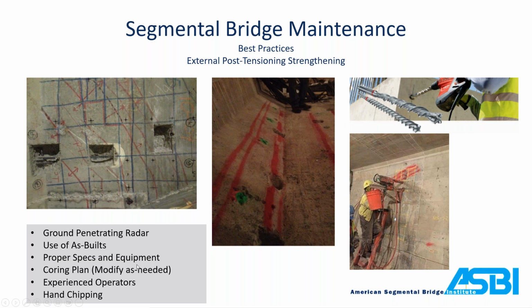Make sure you're using the proper specs and equipment. We learned the hard way that hammer drill bits can cut rebar. So we ended up kicking those off the job. We were under the impression initially that we could use a hammer drill, it won't cut steel, so if we hit steel, we're in good shape. Well, these things did cut steel and we had to make an adjustment to our coring plan. And experienced operators, the guys that are doing the coring or the hammer drilling, they can feel it. They can tell when they're on bar or on steel. Slurry will change to a different color. It'll sound different. It'll feel different. So having experienced operators out there goes a long way when you're doing some of this destructive coring for PT rods or reinforcement.